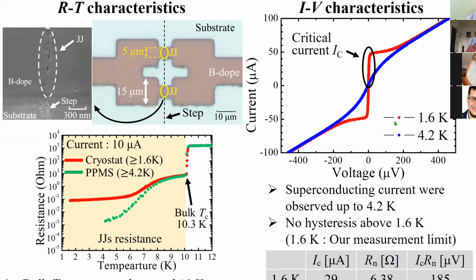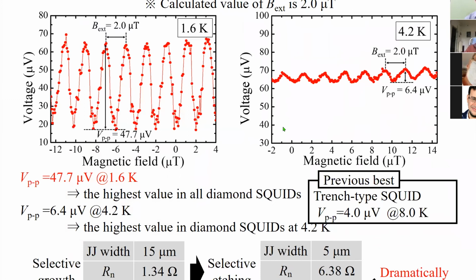I think this is one of the best examples we can show, where the oscillations are very nicely observed. The period is 2 microtesla, and the junction width we obtained here is 5 microns. So this is the minimum junction width we achieved to get SQUID oscillations.